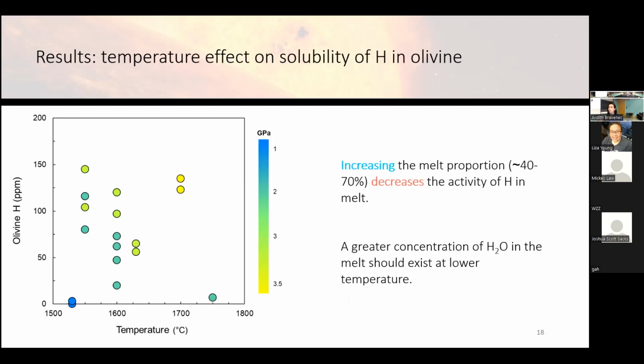The next effect to elucidate is temperature. And here's where things get a little bit more interesting, because you would expect, you have coffee, you have sugar, perhaps you're putting it in your coffee, you increase temperature, you increase solubility. But actually what we see here is that for a given pressure, when you increase temperature, you actually decrease the hydrogen solubility. And this might be a little bit of a counterintuitive result.